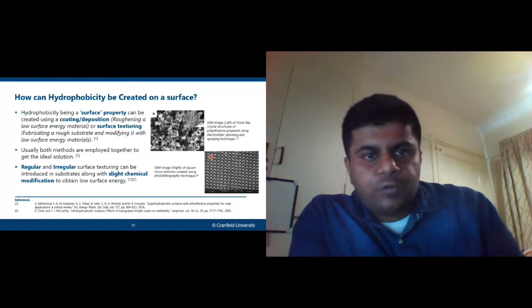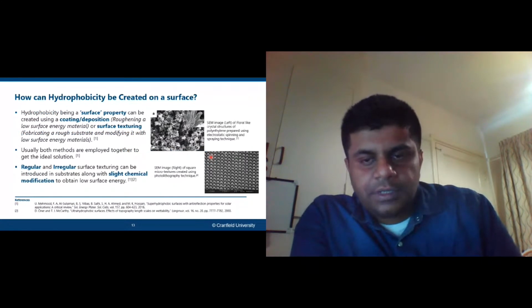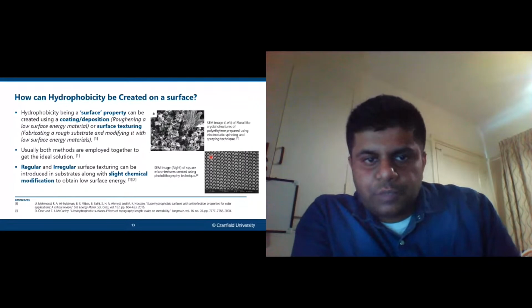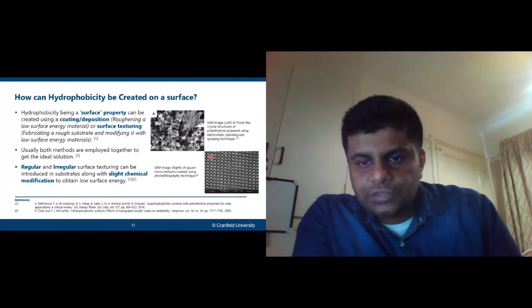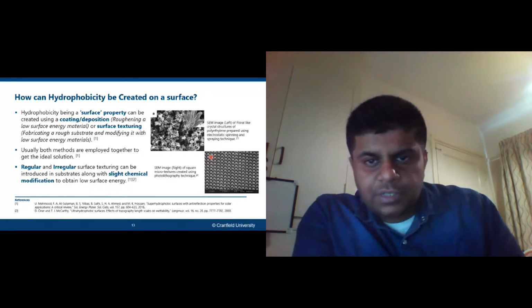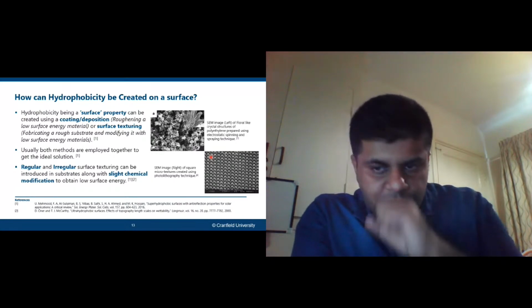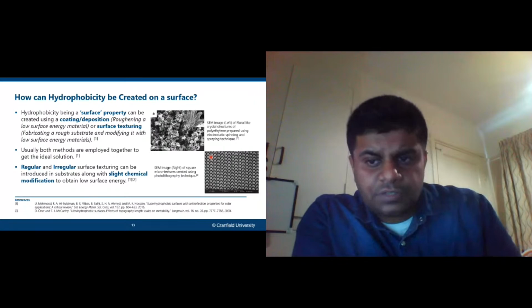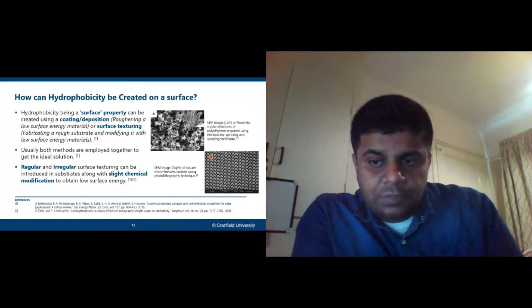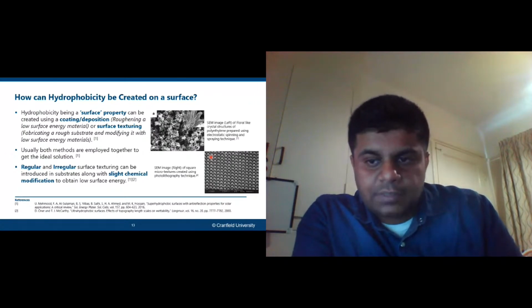So how can hydrophobicity be created on a surface? You basically need to just modify the surface property by either coating it or you can texture it, as shown in the figures. So if you coat it, you're going to end up with a pattern as seen on A. And if you start texturing, you will have a more ordered structure. You can also have an unordered structure, like a fiber structure in which you're going to have a lot of air pockets well dispersed in the substrate layer, which is going to again support this behavior.